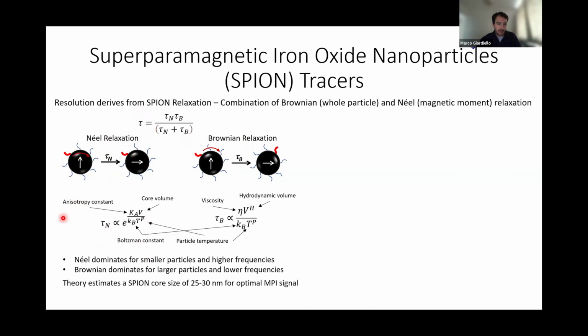And if you break down, without going into lots of the detail of these equations, Néel relaxation is basically dominated by the anisotropy constant of the particle and the core volume. It's more related to the actual particle versus Brownian relaxation. Both of them are related to the particle, they both matter what the particle is. It's just that Brownian is based on diffusion, so it's more dominated by viscosity and the hydrodynamic volume.